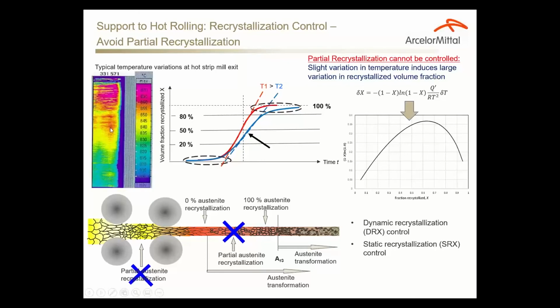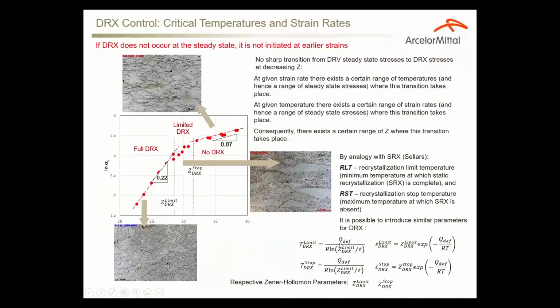And here is the diagram of the actual temperature distribution along the strip exiting the mill. You can see that the temperature variation is 60 degrees Celsius as the bar goes through the mill. So this is quite sufficient to induce very large variation in the fraction of partial recrystallization. So the goal is to avoid partial recrystallization by any means, and that applies to dynamic recrystallization and to static recrystallization.